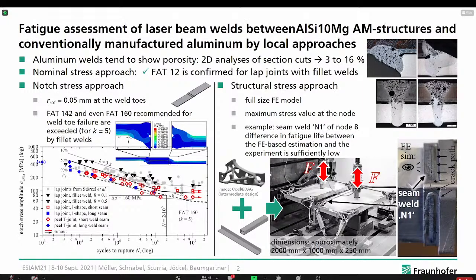And the last thing is just a comment on the mesh size of the real structure that you did the simulation on. It seemed quite coarse, and for getting the stress values from it, in my opinion, you would need a much finer element there, unless you're using methods that are mesh size independent, for example, the energy techniques. In those cases, you can use quite coarse elements to get the strain energy in your part, and then have the prediction based on it. But this is more of a comment rather than I totally agree with it.